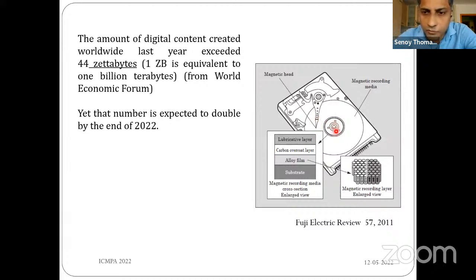If you inspect the disk closely, you could see that it is basically a magnetic alloy thin film deposited on top of a glass substrate. This magnetic alloy thin film serves as the media where we write our information. For example, digital zeros and ones correspond to regions where the magnetization is pointing up or down. In a specific region, the information is recorded by applying a magnetic field using the write head. The read sensor works on the principle of giant magnetoresistance or tunnel magnetoresistance, where the resistance of the magnetic stack changes once the magnetization direction of the adjacent ferromagnetic layer changes.